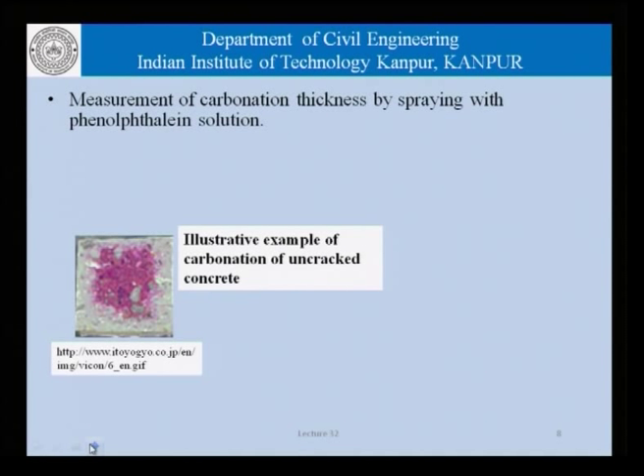Now, as far as the measurement of pH is concerned, one of the most simple things we know from high school is the phenolphthalein test. We know that phenolphthalein turns pink in high pH. So, now if we have a concrete surface such as the one that is shown here, and we spray phenolphthalein on it, we can identify more or less a zone here